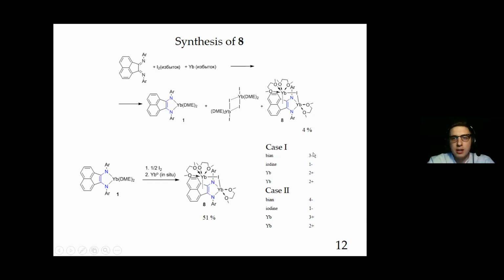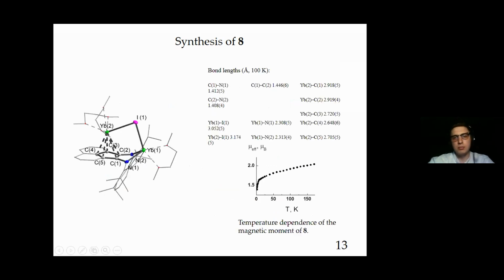One of the isomers should consist of BIAN-3, and another possibility is where the DPP-BIAN is of oxidation state of -4, while one of the ytterbium atoms should be +2, another +3, or vice versa. But in fact, magnetic chemistry shows that this compound again preserves both atoms in the +2 state, and the magnetic moment of the compound is very close to 1.73, which stands for anion radical 3- state of the BIAN ligand.